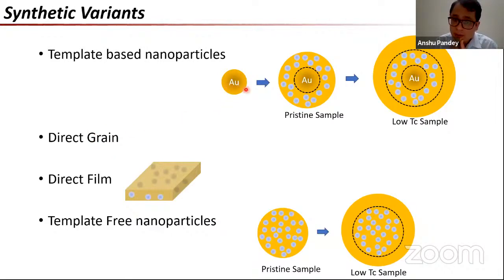Okay, fine. In terms of template-based, direct film, and template-free, all three have been measured, and all three have identical properties. In terms of stability, certainly the template and template-free are the better ones. But they have their own handling problems and synthesis problems. They are very, very complicated to make. The direct film is a simpler one, which allows a quicker verification of the same properties. And at the end of the day, these are powder that you have. In all of these cases, you have powder material. So with a grain, by grain I indeed mean powder.